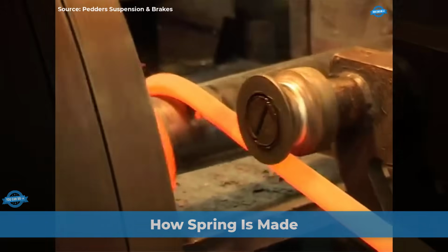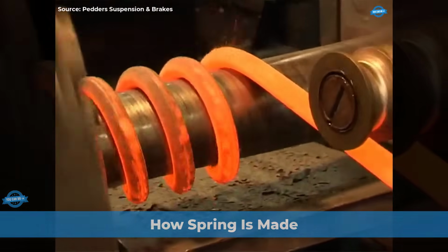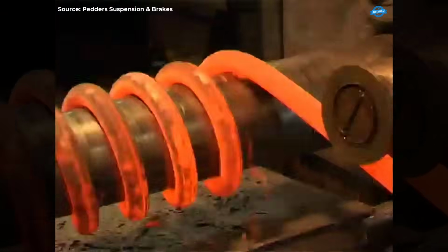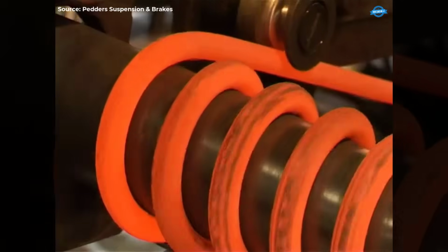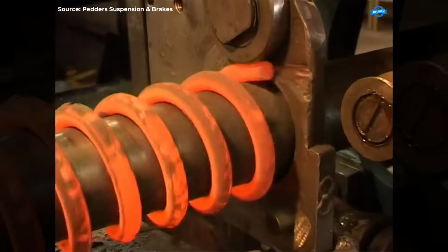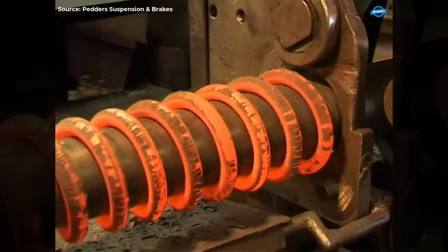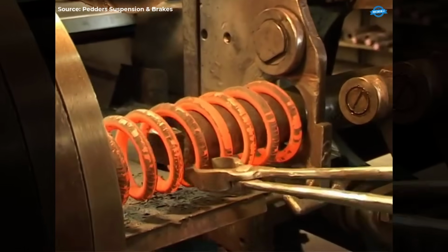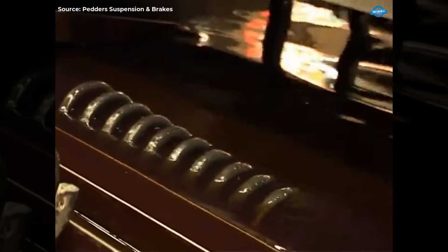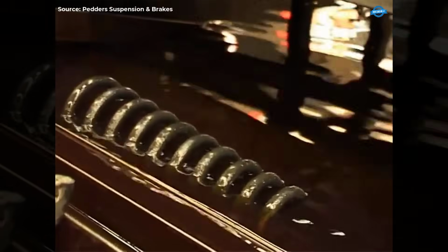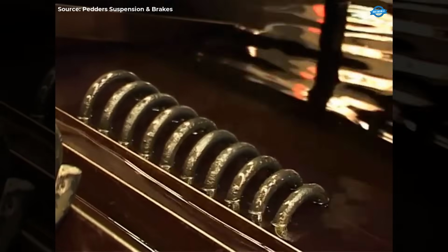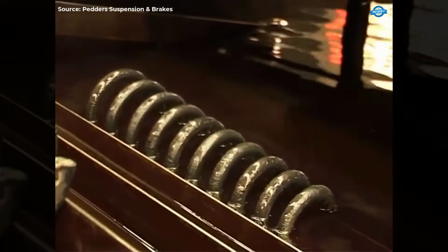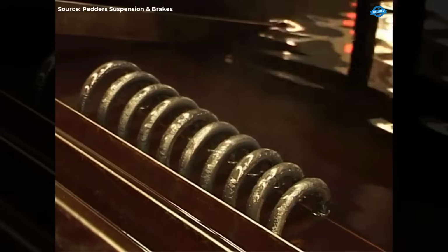The spring steel wire is heated to nearly 1,000 degrees Celsius in a walking beam gas furnace before being coiled on a CNC computer-controlled coiling machine. This hot coiling process ensures consistent results in the finished spring. After coiling, the spring is transferred to a quenching tank, where it is hardened for strength. The oil in the quenching tank is circulated and cooled to prevent hot spots on the coil's surface as it quenches.